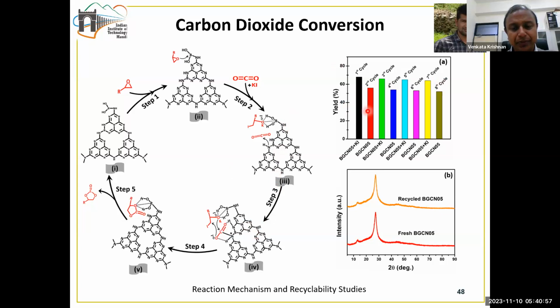And we also did the, since this catalyst is heterogeneous in nature, we also did the recyclability of our heterogeneous catalyst. And after every cycle, we take out the catalyst, we wash it with water, and then use it for the next cycle. So in this regard, the potassium iodide, which is soluble in water, gets lost during the process. That's the reason we have to replenish this potassium iodide after each cycle. But nevertheless, we were able to demonstrate that the catalytic activity is preserved despite multiple cycles. We also did a detailed postmortem analysis of the recycled catalyst or the spent catalyst, and we were able to understand that the catalyst maintains its structural integrity after multiple cycles.